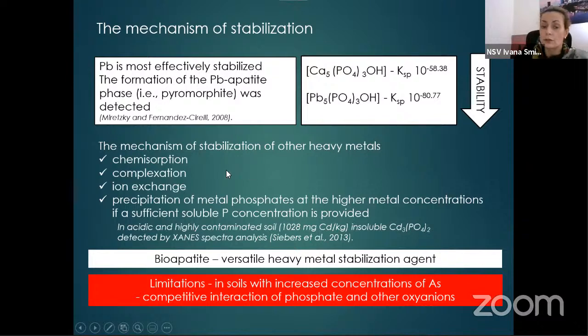The mechanism of the stabilization of other cations, for example, zinc, cadmium, nickel, cobalt, very much depends on the properties of the soil and on the concentration of the element in the soil. Chemisorption can occur both on the bioapatite and on other components of the soil. And then the complexation, ion exchange, and especially if metal concentrations in the soil are very high, the precipitation of new phosphate phases was detected using instrumental analysis.